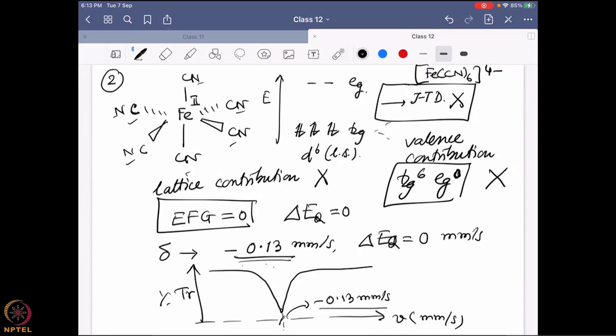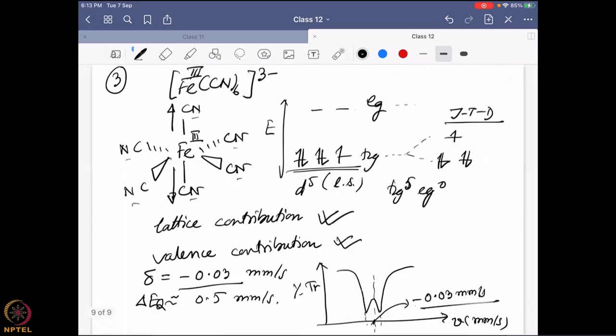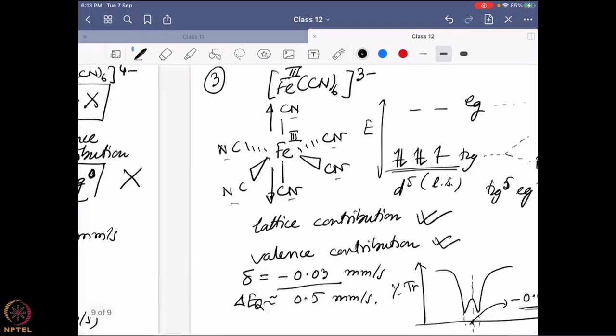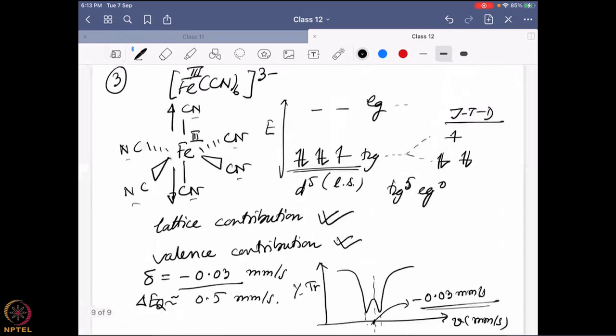So what is the expected thing? If you have a low oxidation state, that should lie on the positive side, and iron 3, which is a higher oxidation state, should lie on the more negative side, but it is showing the opposite trend. Why is it so? That is because the measurement also depends on the temperature. So sometimes the temperature has a huge role to play. And over here, the temperature where the iron 3 is measured is not the same as for the iron 2. So that is why it is showing the data on the more positive side.